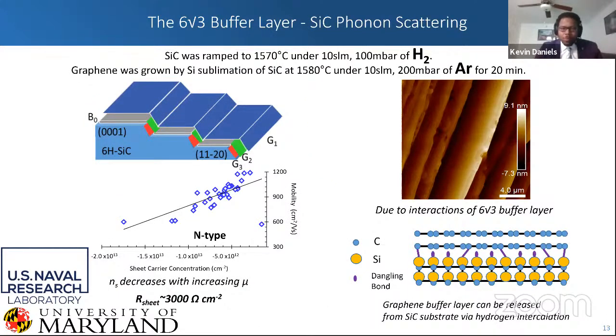Now, as I said before, you have this issue of the silicon carbide phonon scattering, as well as just how graphene grows on silicon carbide. Again, this is step flow mediated. So your silicon is flying out from the step edges in the 1, 1, 2 bar 0 direction. And so you end up with additional layers in that region, as well as this 6√3 buffer layer that's actually binding the substrate to this graphene layer here. As a result, you end up with pretty low carrier mobility. As you remember from the previous slide, it said graphene should be 100,000 centimeters squared per volt second. But because of this electron phonon coupling, our mobility is actually, to be honest with you, pretty on par with what silicon is, which means that, for the most part, it's not that big of an improvement, right?